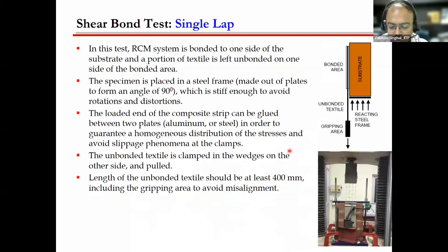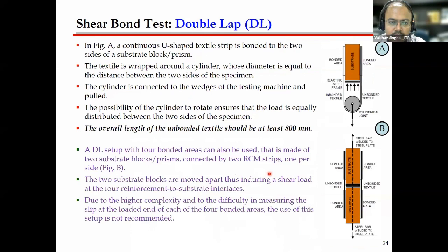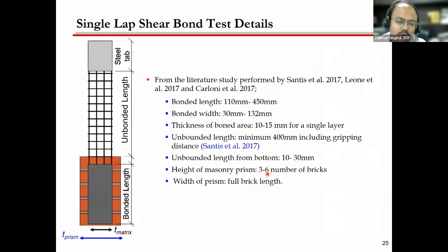The single lap shear bond test is quite easy. You can do it in the lab. You can develop a setup. This is the setup which we have developed at our lab to find out the bond strength. The double lap test can also be done, but the testing setups are more complicated and also more challenging. So we adopted the single lap shear bond test, and based on the literature, we developed our own setup.